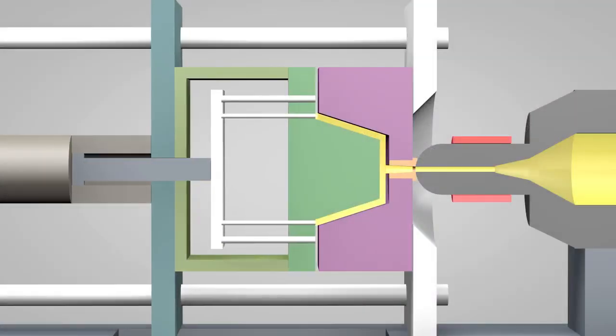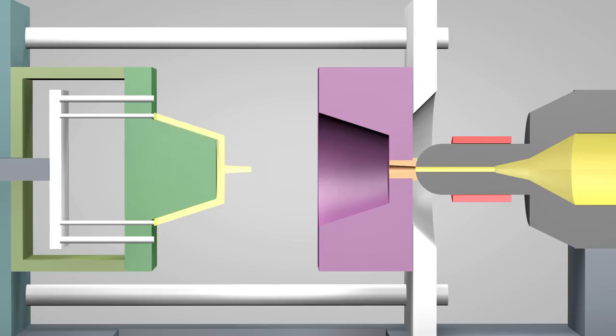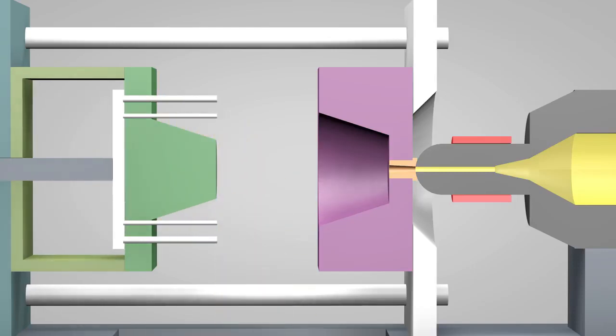As the mold opens, the volume increases without introducing air, which creates tremendous suction that holds the mold together. So at first the mold slowly opens several millimeters to allow air to rush in and break the vacuum, and then the mold quickly opens the rest of the way so the part can be removed. These precision machine steel molds can cost hundreds of thousands of dollars.